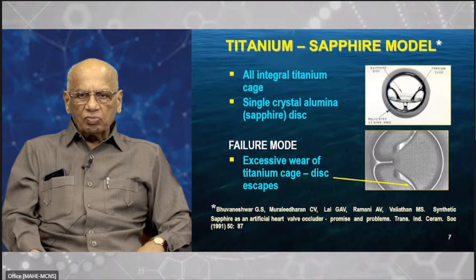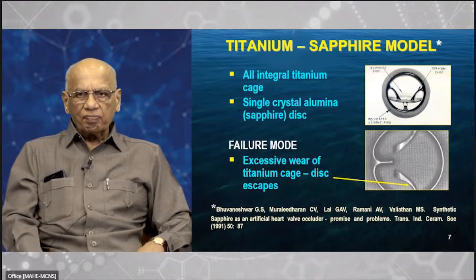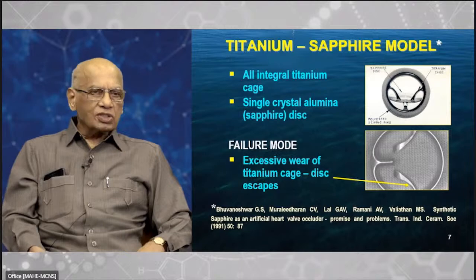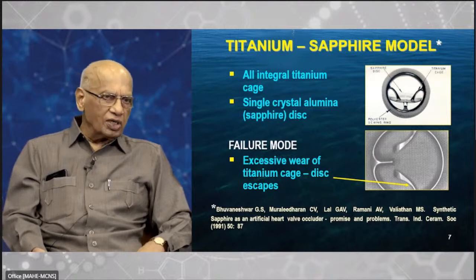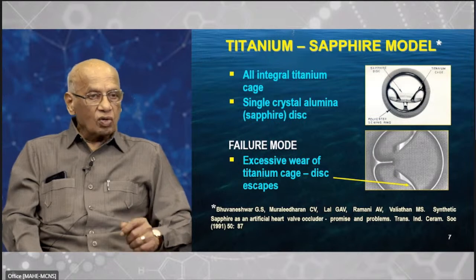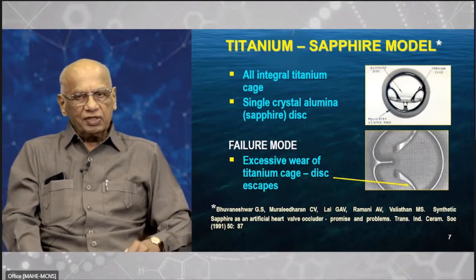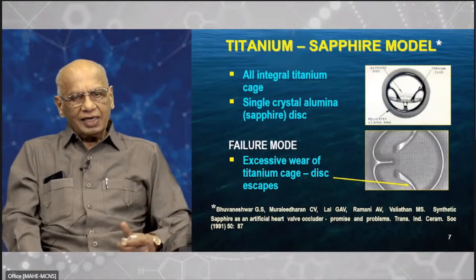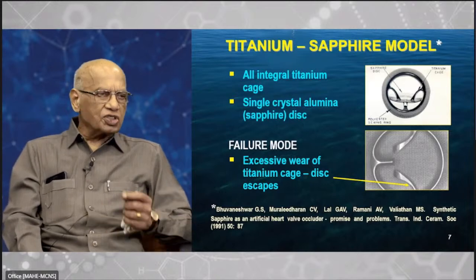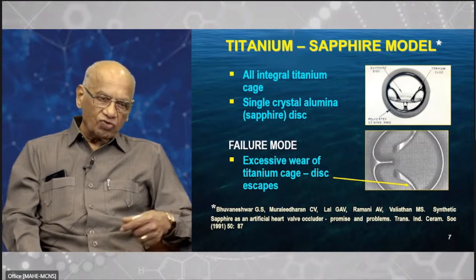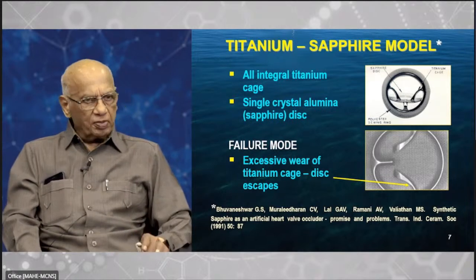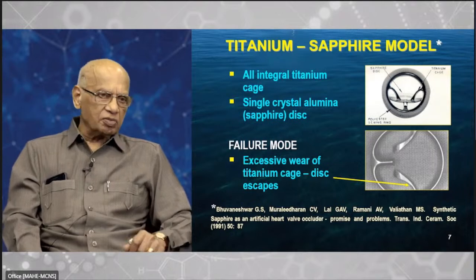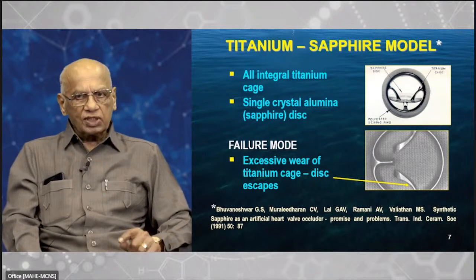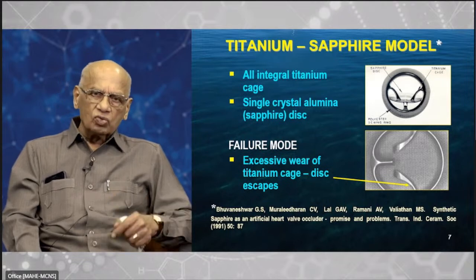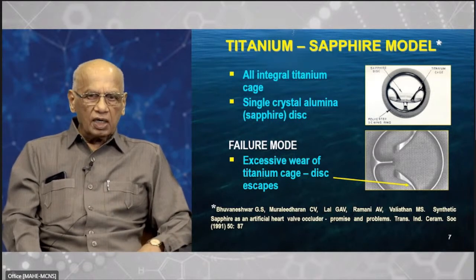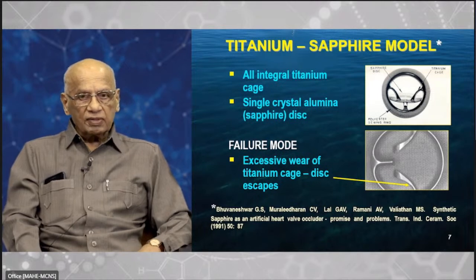And failure mode, when this was tested: the disc is single crystal alumina. We had changed that also because earlier on polyacetal, one difficulty, even though it is very cheap, is that when you put it in the autoclave, it absorbs a certain amount of water and there is a dimensional change. Even though if you leave it outside at room temperature for 24 hours it comes back to the original dimension, still it is unacceptable in a clinical application. So we wanted to change the disc also. The disc had come to single crystal alumina, which is very hard, otherwise an excellent material.